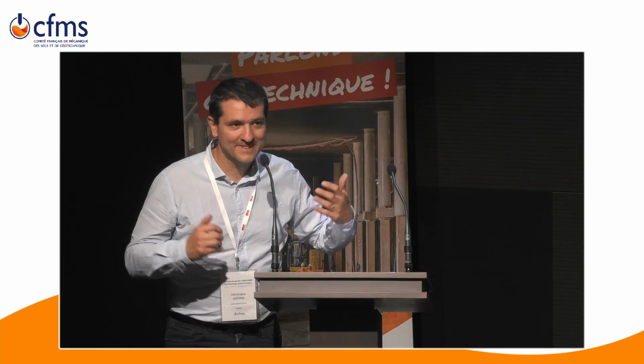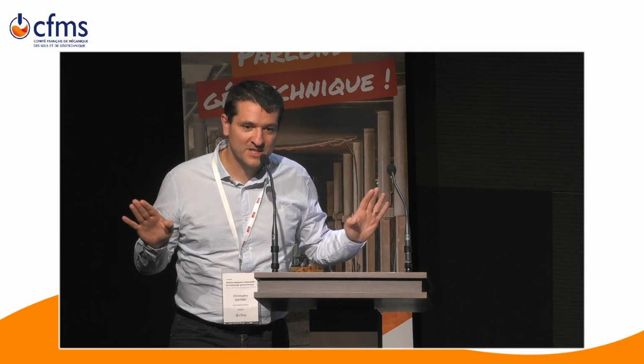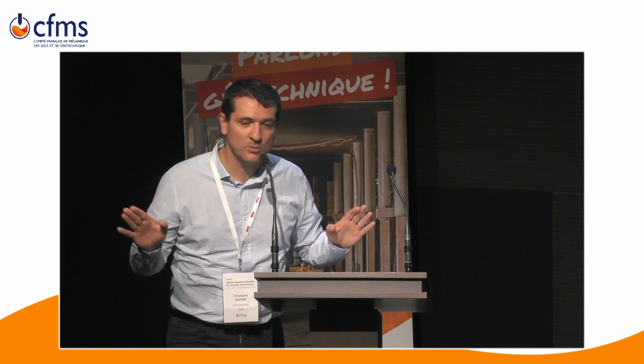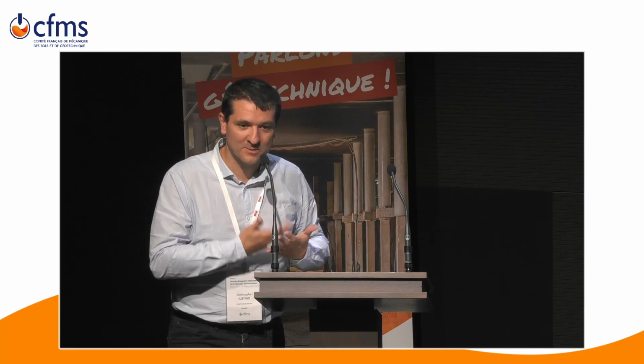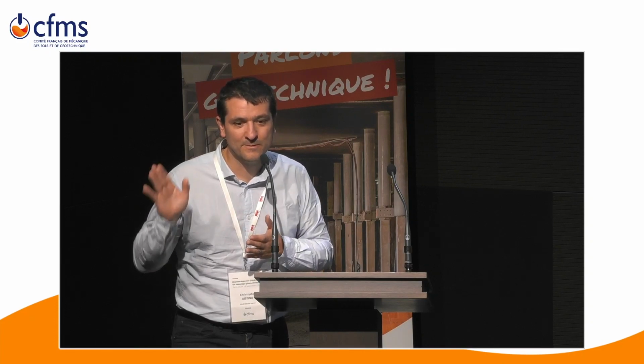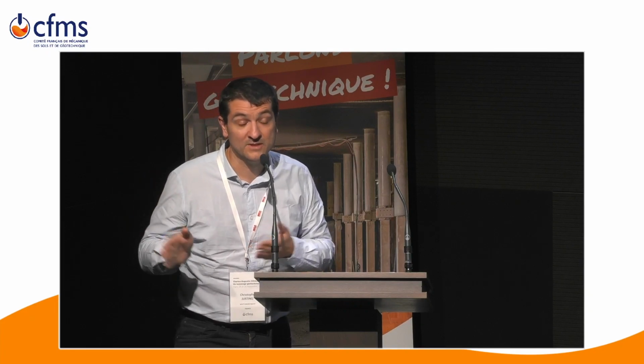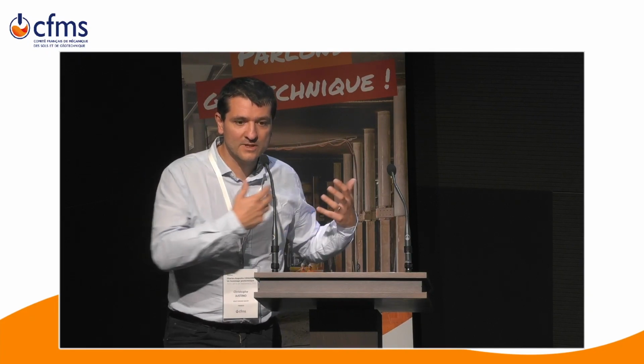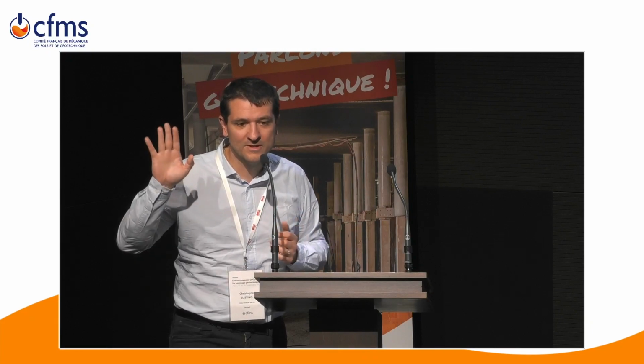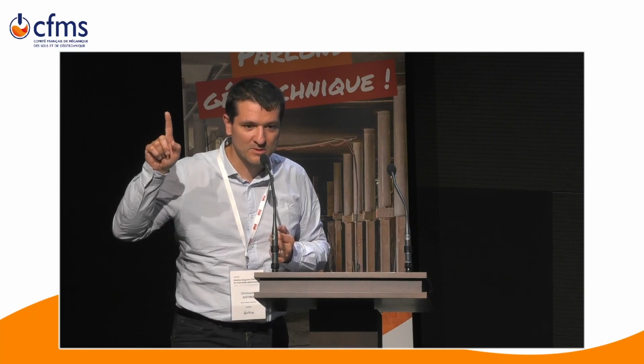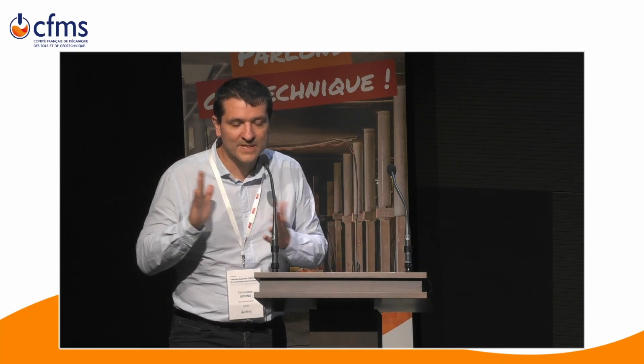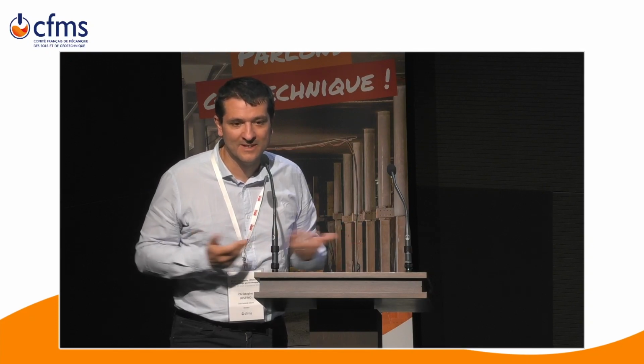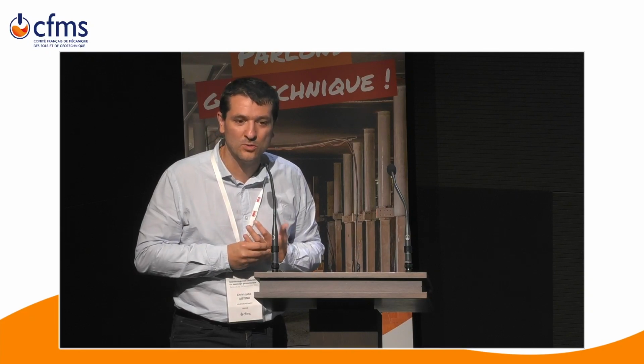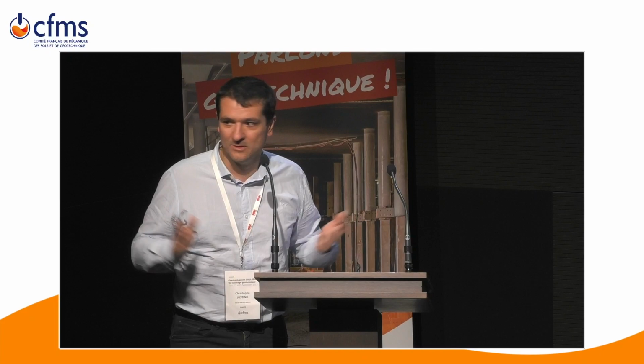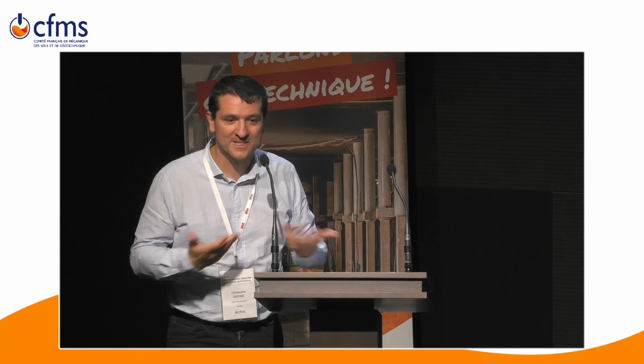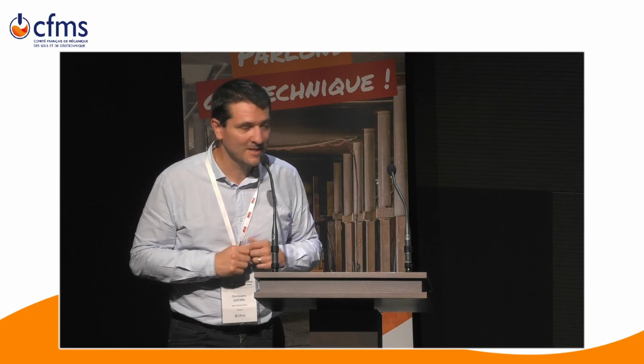When it comes to surface finishing, obviously for civil works, there is a lot to do with the concrete mix design, but there is also a lot to do with the formwork, the finishing. In our case, what we are going to do is avoid bleed. Avoiding bleed will avoid as much as possible this aspect of channels at the surface. But because of the way it's cast against the ground, it's as cast, so it's complex to work on the surface finishing. If you really want something better, you need to put a precast thing.